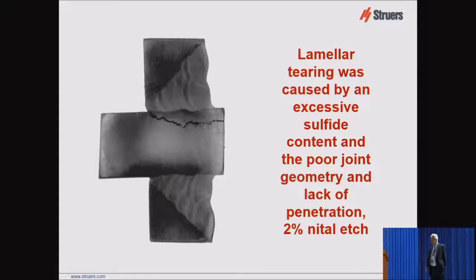And it had an excessively high sulfur content in the steel. It was legal by the standard, less than 0.045% sulfur, but it wasn't a lot less than that. And if you're doing this kind of welding process, you really need to have much lower sulfur than that. But the poor penetration is a serious problem.